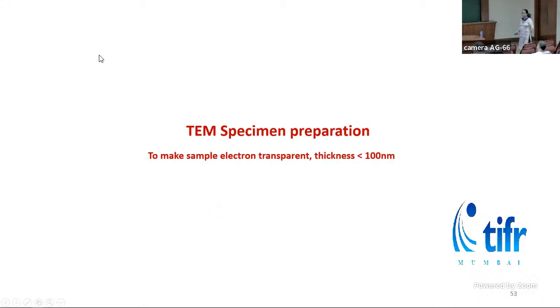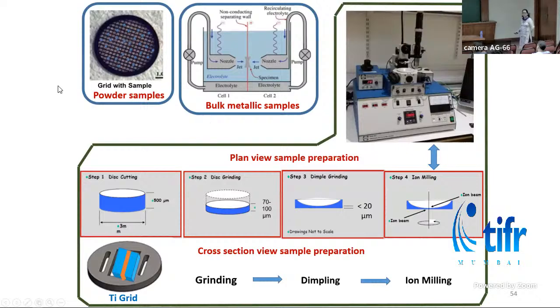As I mentioned earlier, TEM sample preparation is a very tedious job. The job is to make the sample electron transparent, and thickness should be less than 100 nanometer. If we have a powder sample, we can simply sonicate it in a suitable solvent and then put a drop on a carbon grid. If we have a bulk metallic sample, it can be prepared by etching with electrolyte.